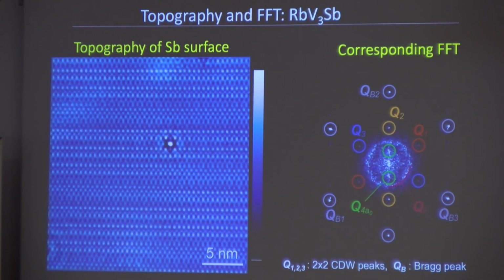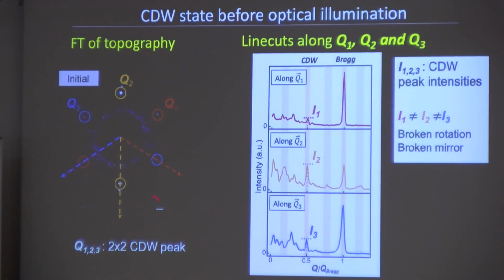So the first, these are the charge density wave peaks. The first is these 1, 2, 3. These are the 3 CDW peaks. They're all different intensities. Now look, the Bragg peaks are also different intensities, and they're not different intensities in the same way. This is tall, this is short, this is medium, this is medium. It's really difficult to say how these two things are correlated. So this is why I'm saying it's really difficult to know what information is contained in the intensity of the